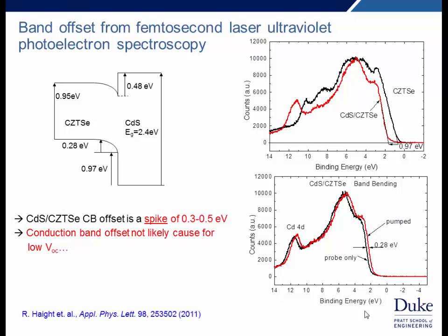We've examined this band offset using UPS, which basically measures the valence band offset, and then we use the known band gaps to get the conduction band offset. And for a range of different sulfur to selenium ratios in CZTS, so for a range of different band gap values, we find that our conduction band offset is a spike in a reasonable range. And so conduction band offset we do not believe is likely to be a cause for the low open circuit voltage in these films.